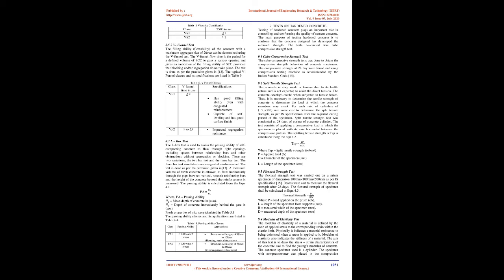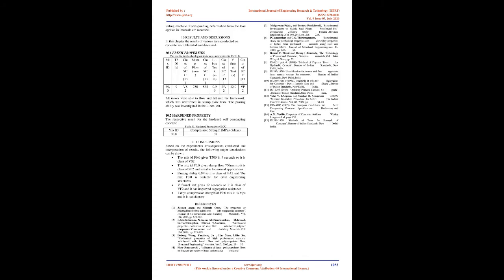9. Tests on hardened concrete. Testing of hardened concrete plays an important role in controlling and confirming the quality of cement concrete. The main purpose of testing hardened concrete is to confirm that the concrete design has developed the required strength. The test conducted was the Cube Compressive Strength Test. 9.1 Cube Compressive Strength Test. The Cube Compressive Strength test was done to obtain the compressive strength behavior of concrete specimens. The compressive strength at 28 days was found using a compression testing machine as recommended by the Indian Standard Code IS 516.